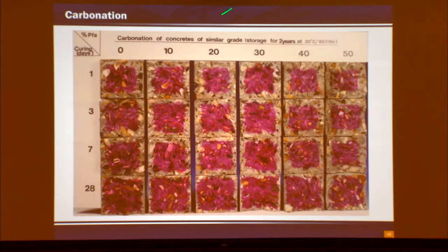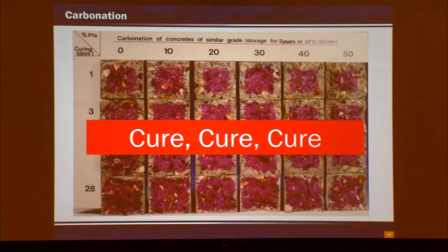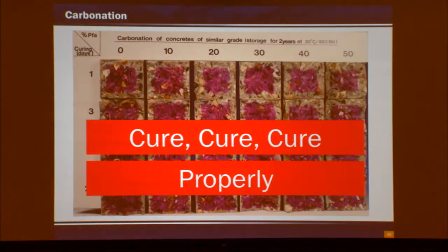This is an interesting slide. We have curing days versus percentage of fly ash. As you see, as fly ash increases, you increase your depth of carbonation. Why? Because fly ash consumes calcium hydroxide. Calcium hydroxide acts as a buffer for carbonation. So we're doing something good, but we're kind of doing something bad for carbonation. But the saving grace is, well, if I cure, then I have less carbonation. Look at the difference between 28 days of curing versus that. So the main takeaway here is cure your concrete, but cure it properly.